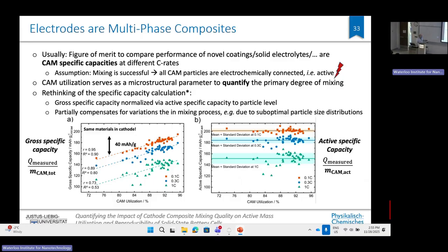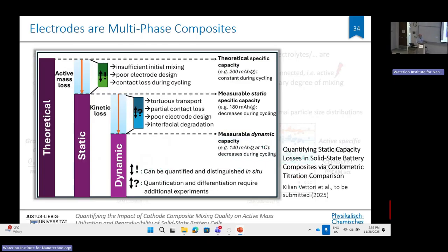And then the data for the different cathodes, each dot here is one cell, essentially, at different C rates. So this is 1C, 0.3C, 0.1C. You see these data really scatter quite a bit, but when you order them with respect to the utilization, the fraction of cathode particles being connected, and normalize to that, then all these data nicely fall onto one line, onto one capacity value, and that is then correct. Then you can really judge, okay, my cathode material has this capacity at a given rate, and you do not include into your judgment of the kinetics of your cell those particles that are not connected. So that's a very important step. And this is in this graph here.